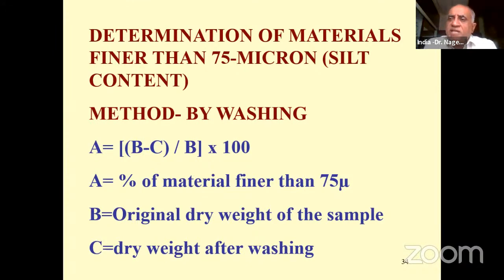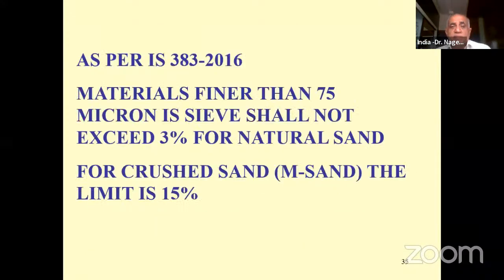75 micron is a very simple test. You take 100 grams of sand and do the wet sieving. All fine particles will pass through the 75 micron sieve. Whatever remains, you can keep in an oven and find out the weight. So whatever is less than 75 micron passes, and we can express the weight as a percentage of the weight of the original sample taken. That will tell what is the percentage of material finer than 75 micron.